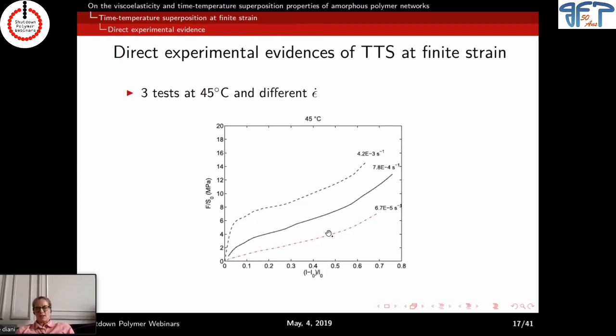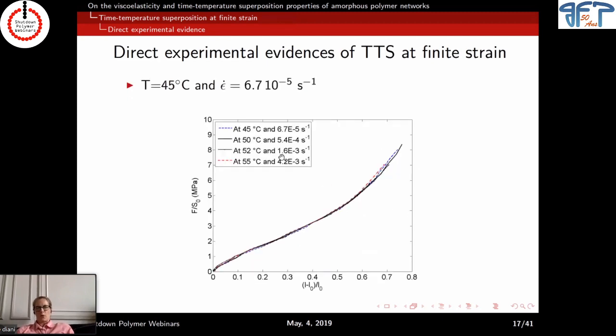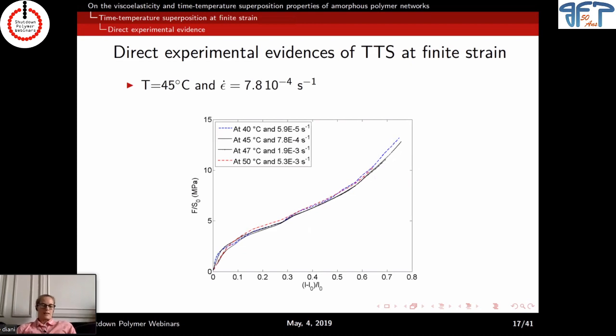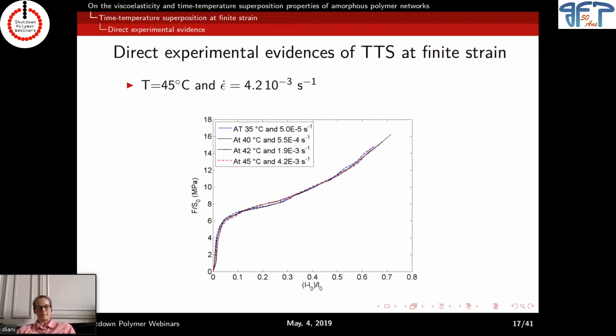And for each response, starting with this one, we change the temperature and look for the strain rate that gave the same stress response. And we found, as you see, that for temperatures within a 10-degree range, we could find a different strain rate that gave the same stress strain response. That means that at least in the rubbery state, we were able to find a shift factor to have time temperature superposition. And it was true for the second stress strain response and the third one.